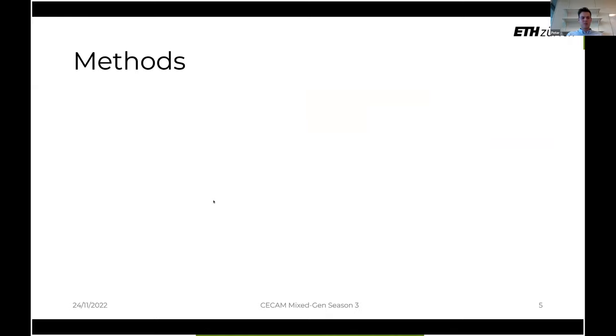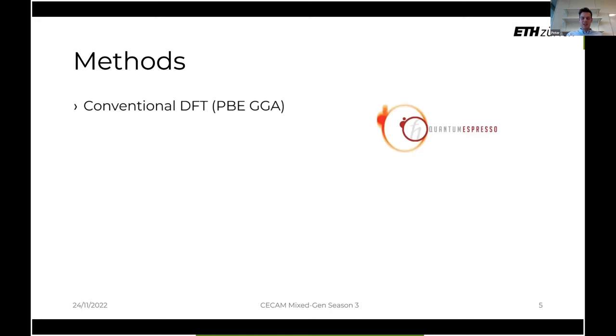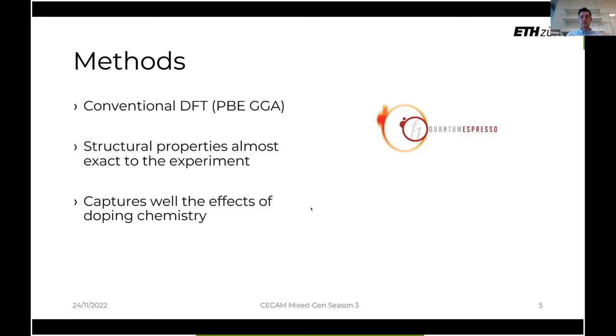And so, in particular, I would like to just spend one slide on the methods that we use, because these are quite different from what was just talked about. Indeed, in the work that I will present now, we only use conventional DFT. We stay at the PBE level, and we describe our system without any added plus U or any added corrections. This is because we see that the structural properties of vanadium dioxide are almost exact to the experiment. So they're very good without addition of any correlations. And we also believe that by treating the system using DFT, we can capture well the effects that the addition of a different chemical dopant has on the system.